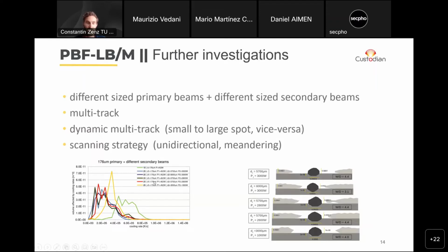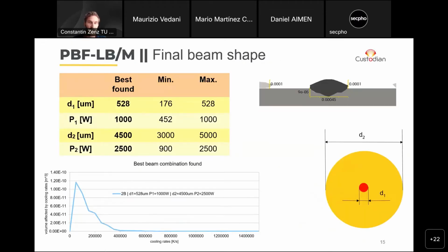Then on the bottom you can see, as an example, the information which is extracted from these different simulations. We got different cooling rate plots, and you can see that the further left such a curve is on this scale, the better. This means overall we have lower cooling rates. For example, this green one is quite bad because lots of volume is affected by high cooling rates. We also looked at the geometry of the weld bead which is achieved, and looked for a good width to depth ratio, which is also favorable in terms of cracking risk.